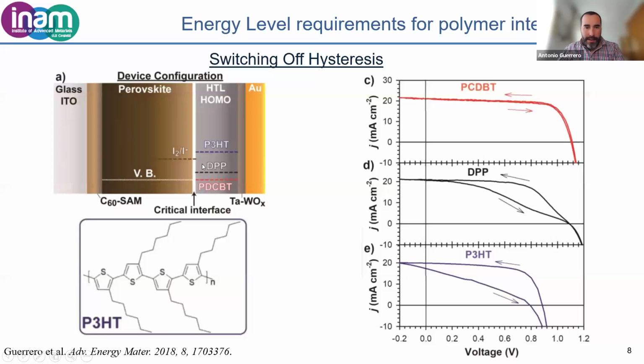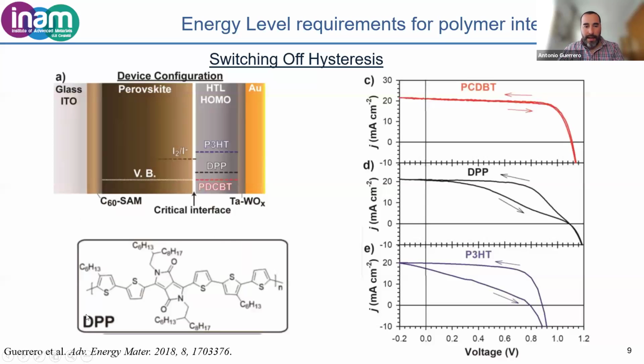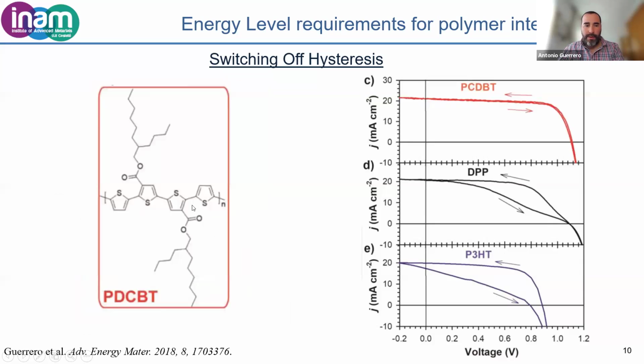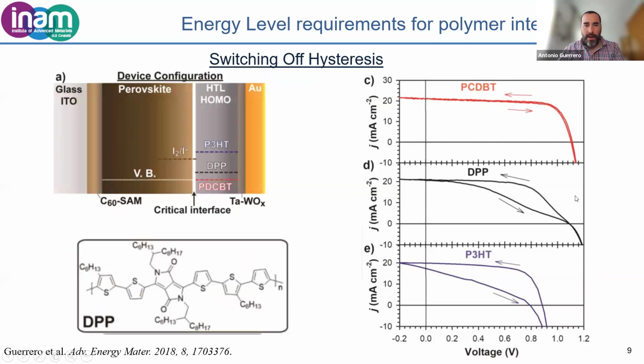But then if we replace this material by a polymer called DPP, we totally modify the response in terms of hysteresis. And we can even suppress the hysteresis when we use the polymer PDCBT, as you see here. So when we use this type of polymer, the hysteresis is not observed. Then we need to think about what is the difference between these polymers, and one of the main differences between them is the HOMO level of this selective contact.